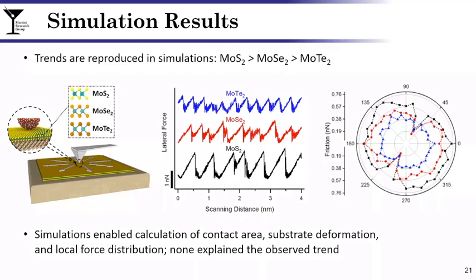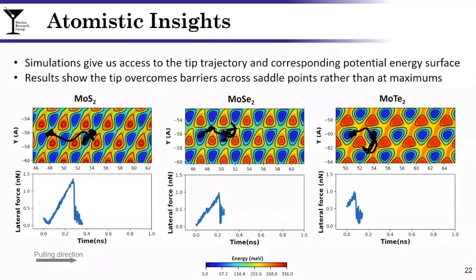So we came back to our potential energy surfaces. What I'm showing you here, the colorful pictures are the potential energy surface. That is the convolution of the model tip and the substrate, where red is high energy and blue is low. The black line is the trajectory of the tip as it moves over the surface. And below you can see the corresponding lateral force or friction trace. There's two key points to note here. First, the difference between the maximum and minimum energy, so the energy barrier height on all three of these TMDs is about the same. But secondly, the tip doesn't actually go over the high energy barriers. Rather, it goes around the high energy barriers and crosses at the saddle points.